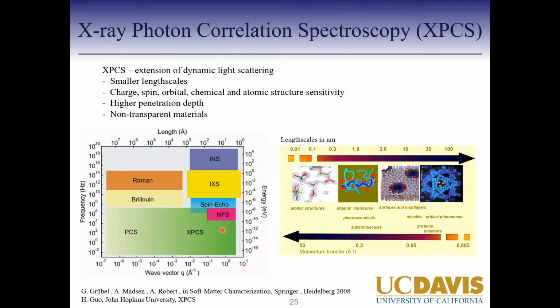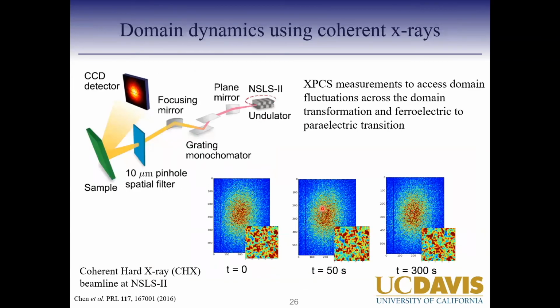Correlation spectroscopy, especially in the light regime using lasers, has been widely used to study fluctuation in glasses as they go through phase transition or glass transition. But with such small displacements of ions and domain structure, you need to have access to small length scales. So correlation spectroscopy techniques have been adapted in the X-ray regime, so you can get access to these angstroms, 1 angstrom to 100 angstrom regime, which is where X-rays can look at the material. So this experiment was done at NSLS2, National Synchrotron Light Source 2 at the Coherent Hard X-ray beamline.